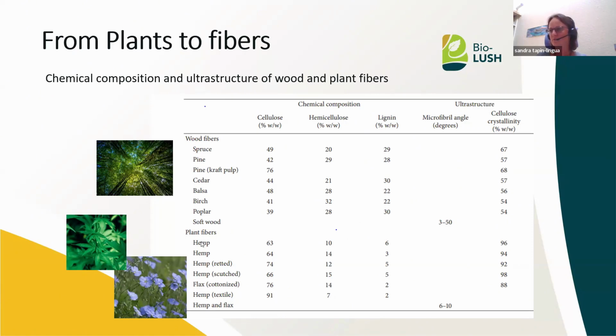If we consider the annual plants, here are just some examples with hemp and flax, we see that depending on the type of fiber isolated, we can have really pure cellulosic material with low content of lignin and high content of cellulose. And the crystallinity of these materials is really different, with really high crystallinity for annual plants compared to wood.